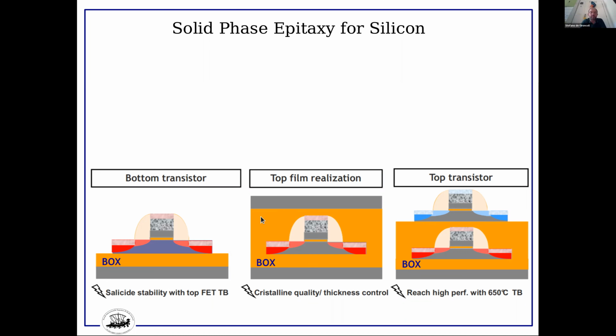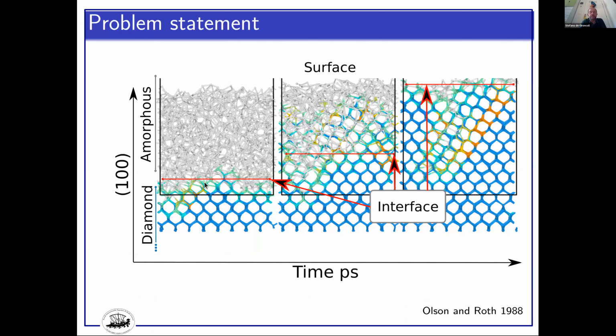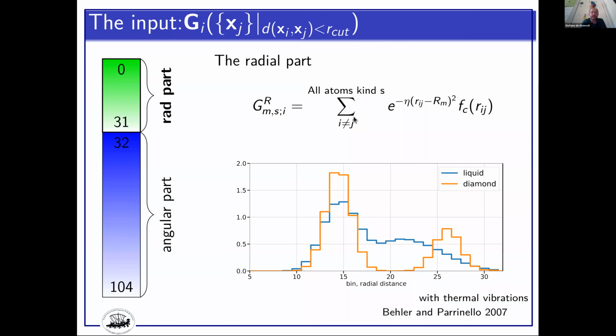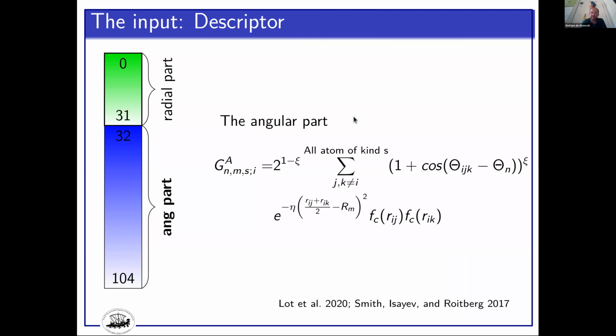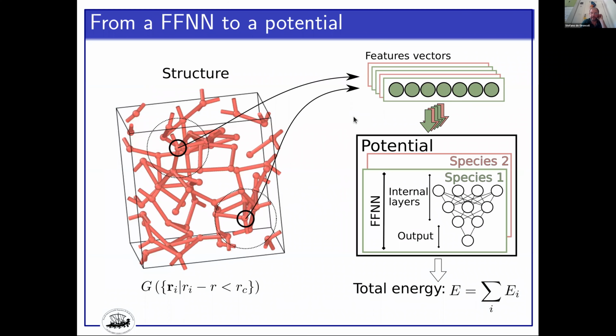And so basically what you want to model is the recrystallization, from a crystalline structure, of an amorphous overlayer, and at which speed this happens. We generated a potential that is designed for this, for silicon, amorphous silicon, surfaces, etc. So similarly, we use the same Behler-Parrinello radial symmetry functions and the modified angular symmetry functions. We generate a number of configurations and we train, and at the end we generate a potential.